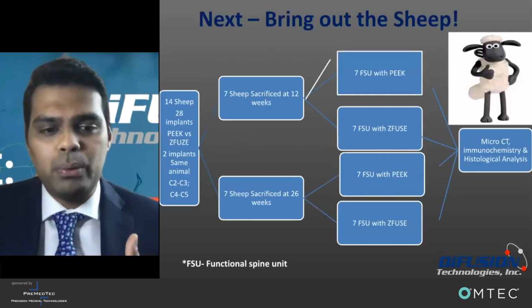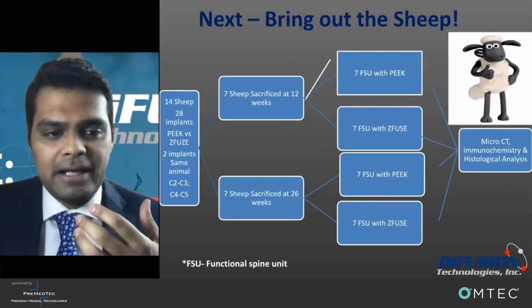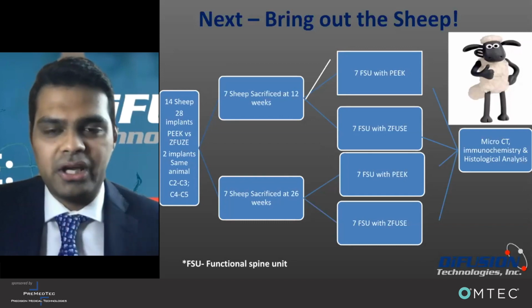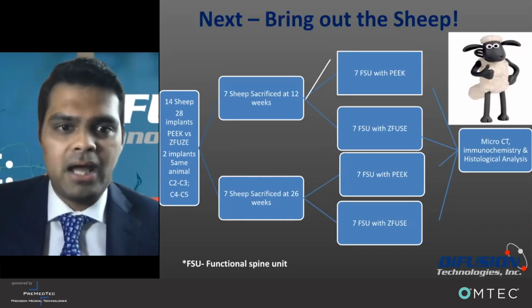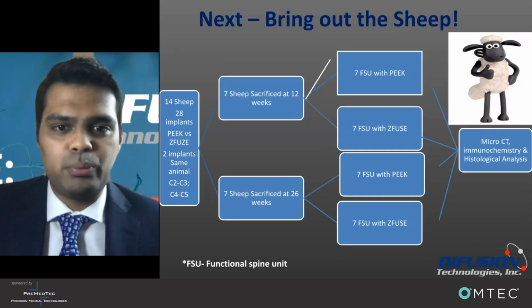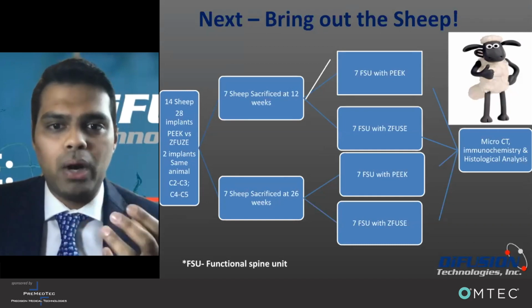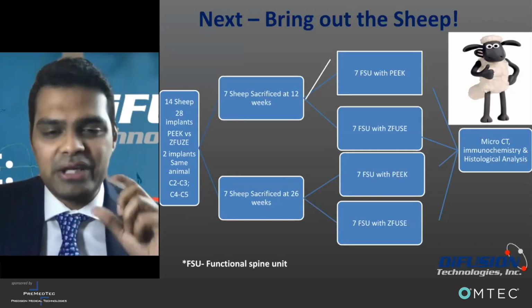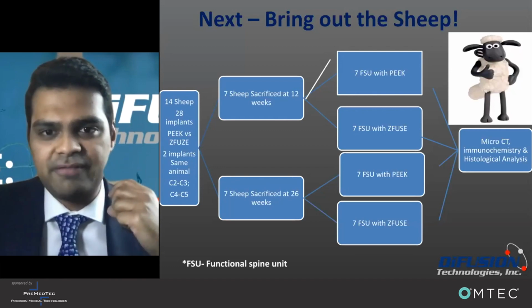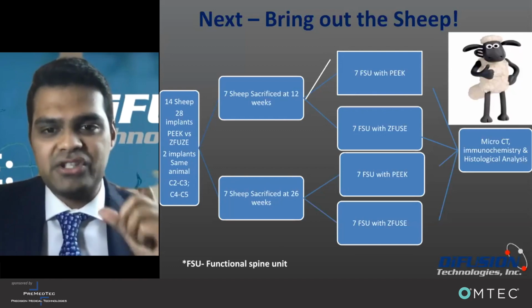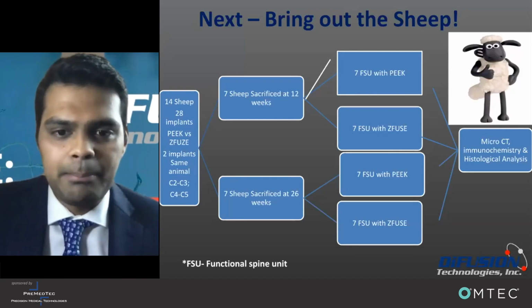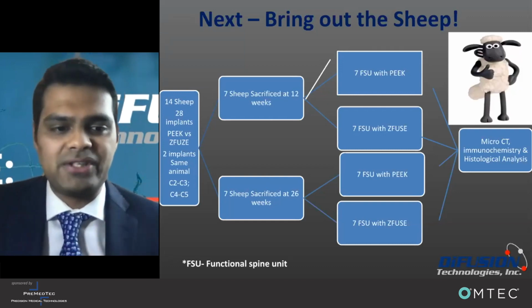So quickly then we went on to elucidating this mechanism in a sheep study. And we basically took sheep. We had two groups, one with PEEK. We had two levels, C2-C3 and C4-C5. So each level had a PEEK and Z-Fuse implanted in it. And we looked at 12 and 26 weeks.